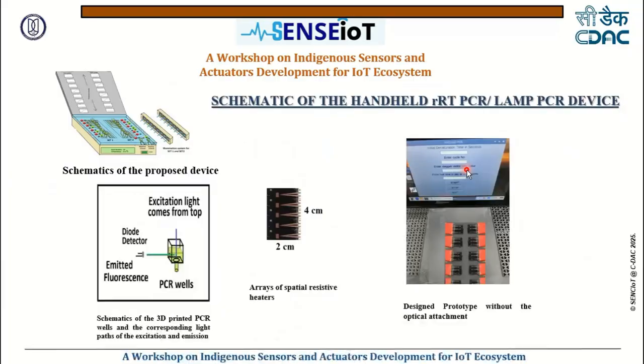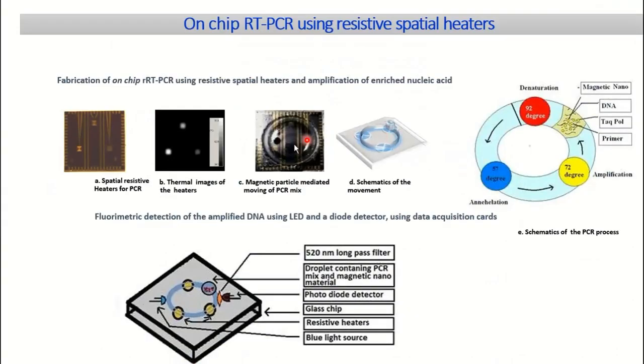So you see that these are the three temperature zones and this droplet. The movie is somehow not working. So it will move on these three temperature zones. This project was funded by BIRAC, in collaboration with CDAC Kolkata, and we have designed more or less the prototype chip. This magnetic nanoparticle can be moved with the use of magnets on top of a stepper motor, and we can program the stepper motor with the magnet so that it pulls the magnetic nanoparticles and the PCR mix, and the PCR can be done in 18 to 20 minutes.